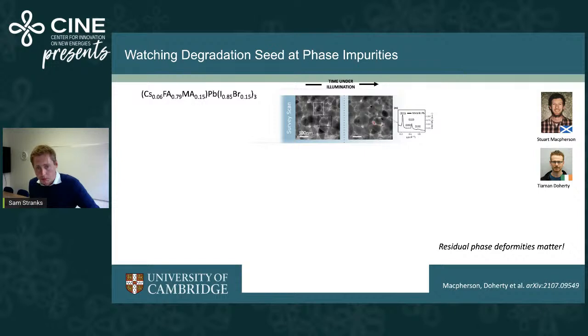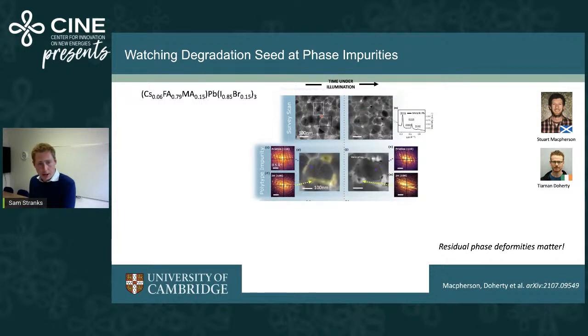You see these tiny black dots scattered around in these local sites. This is metallic lead, so we're seeing some formation of metallic lead. If we zoom in now on one of these regions that does change, we can look at the structure. This grain here is pristine perovskite, but when we look at the grains around it, shaded in yellow, these are actually 2H hexagonal polytypes. So you can see these other phases, and in fact, it's these phases that are photodegrading. As we look at the degradation over time, the perovskite grain is largely, at least in this time snapshot, intact, but we see material loss in particular where these hexagonal polytypes are, and also a lot of metallic lead forming as well.